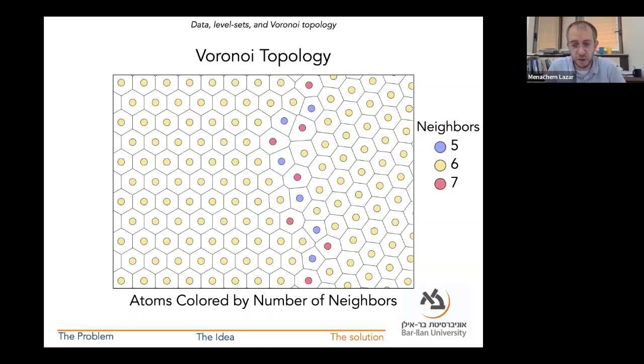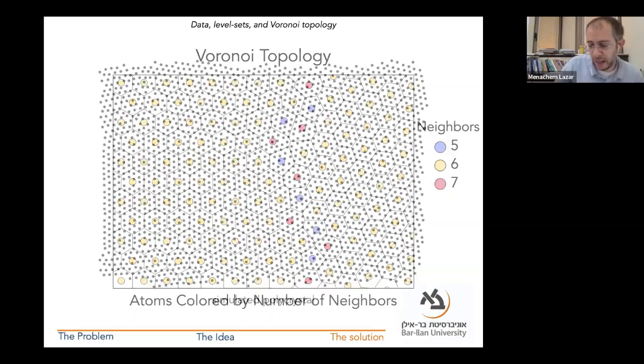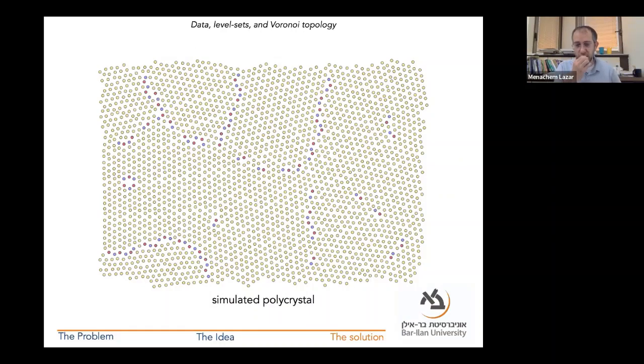Here we have a chain of Voronoi cells that don't have 6 edges each. And that's it. I guess you probably guessed by now, that's essentially what I did before. I colored all the particles according to the number of edges of their Voronoi cells, and in some sense it shows some of the structure in this system.